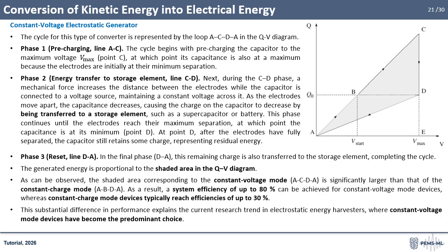During this phase, a mechanical force increases the electrode separation while the capacitor is connected to a voltage source, maintaining a constant voltage across it. As the electrodes move apart, the capacitance decreases, causing the charge on the capacitor to decrease by being transferred to a storage element, such as a supercapacitor or battery. This phase continues until the electrodes reach their maximum separation, at which point the capacitance is at its minimum. At point D, after the electrodes have fully separated, the capacitor still retains some charge, representing residual energy.